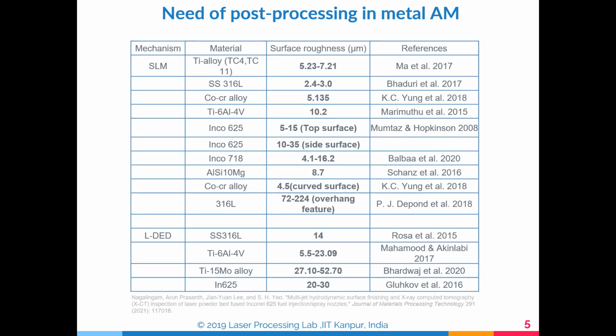When we do selective laser melting, it is not sintering, it is melting. So 100% of the powder particles are melted and allowed to join. If you want to get a sound, good quality product, we always go for selective laser melting. Of course, there is an energy balance you have to do to get the required output. So what are all the materials which work in the SLM process? Titanium alloy, stainless steel, cobalt chromium, Ti6Al4V, Inconel, then we have AlSi, then cobalt chromium, and 316L. So these are the stainless steels.